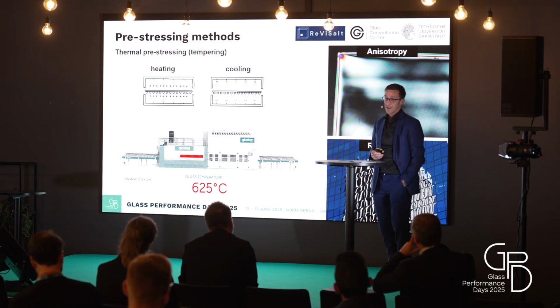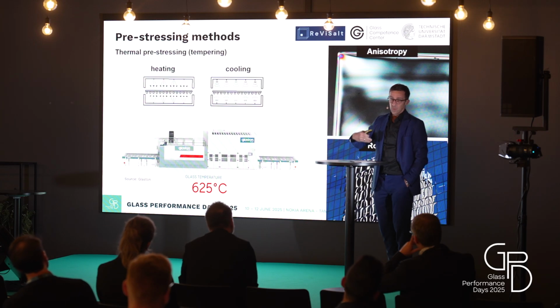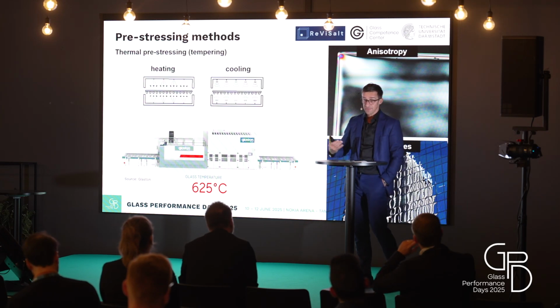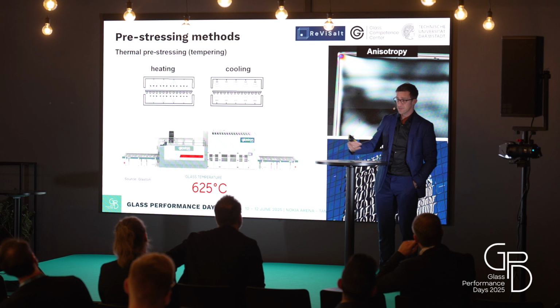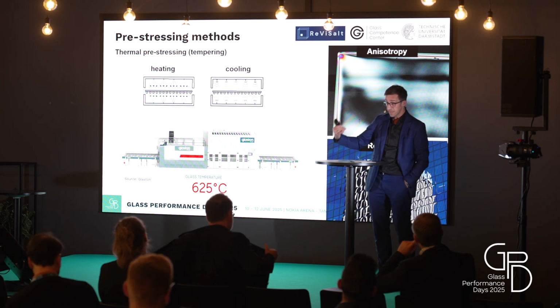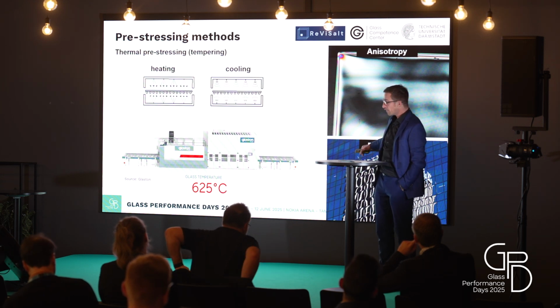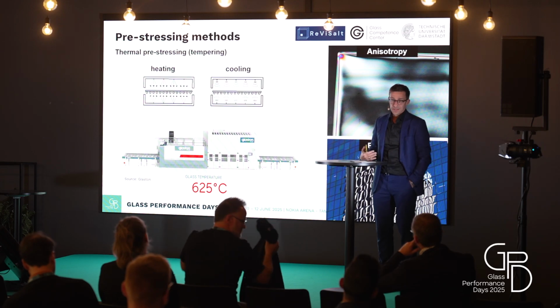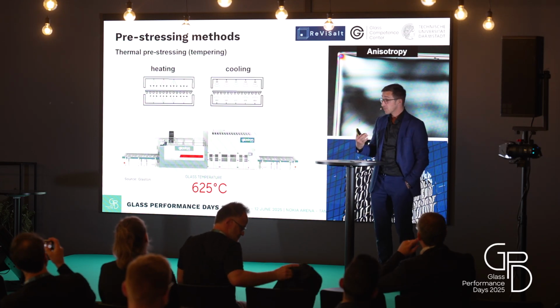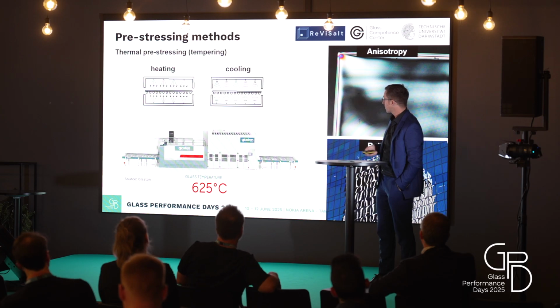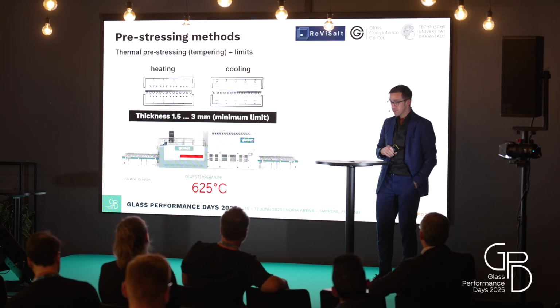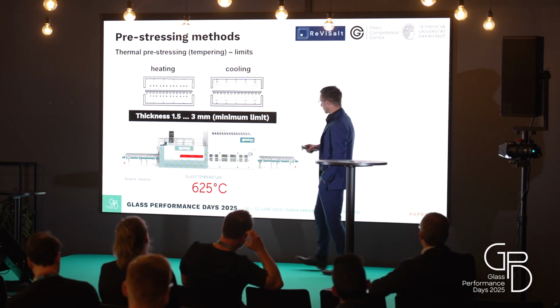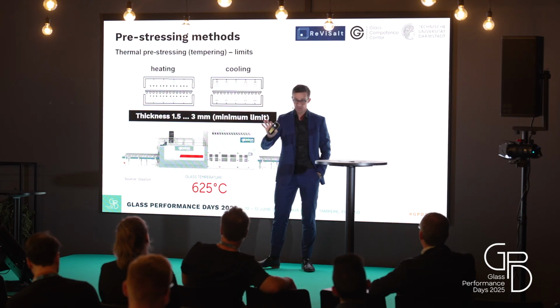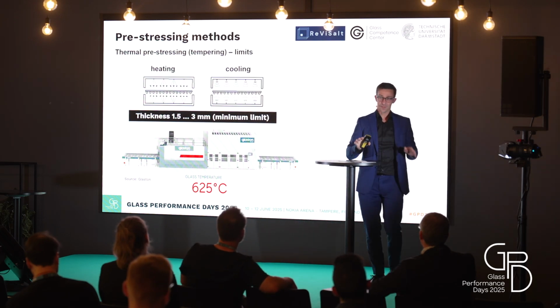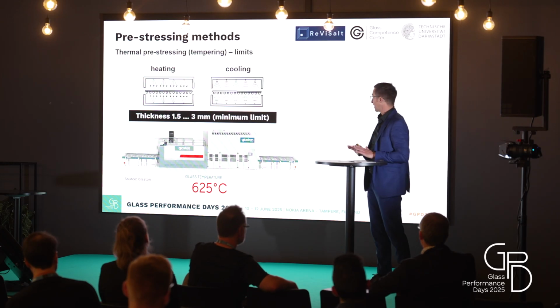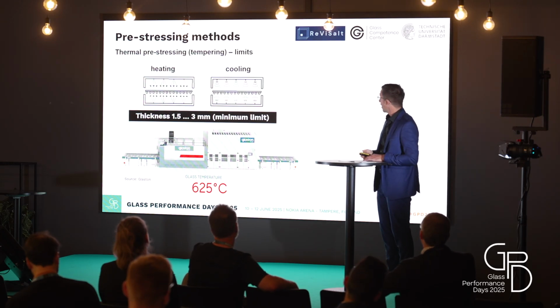But we also have some disadvantages of this process. We have some distortions, roller waves, and so on. There were some discussions yesterday about the distortions, also with the lamination. We have the roller waves, and we also have some anisotropic effects. We don't want this, and the architects don't want this. I think this is clear. And yes, we have limits. The normal furnace can pre-stress a minimum of 3 millimeter. It's also possible to do 1.5 millimeter, but not everyone can do this.